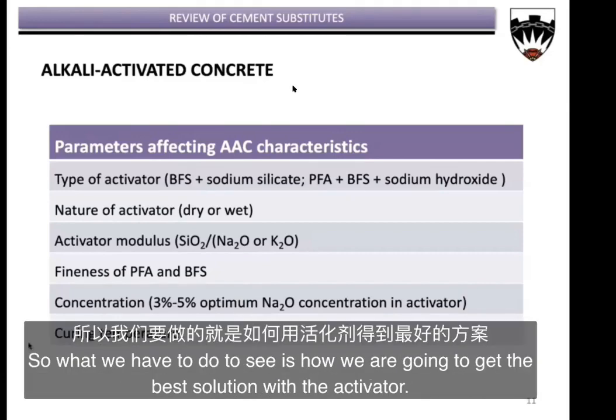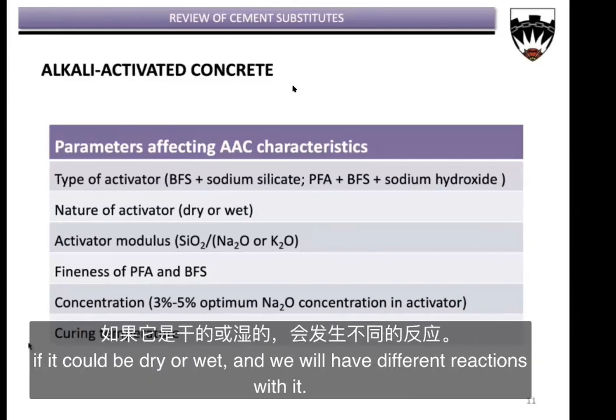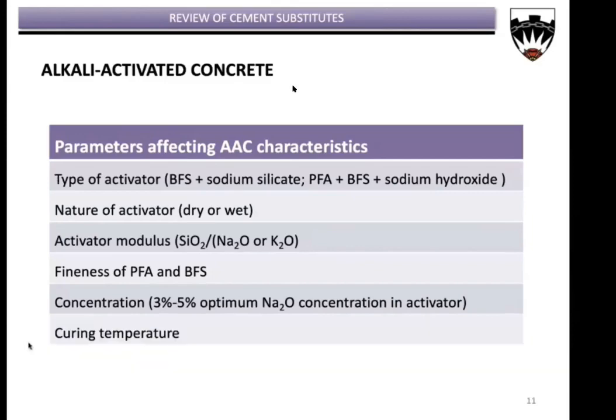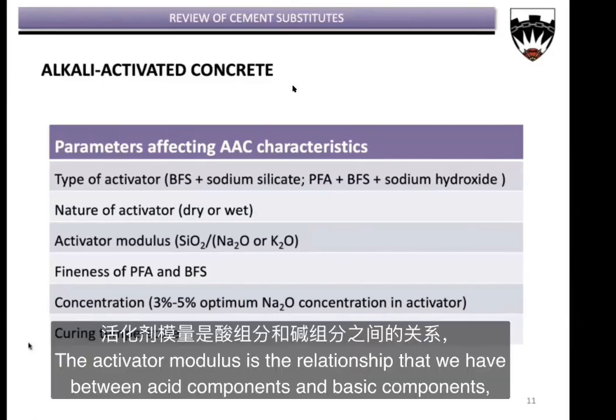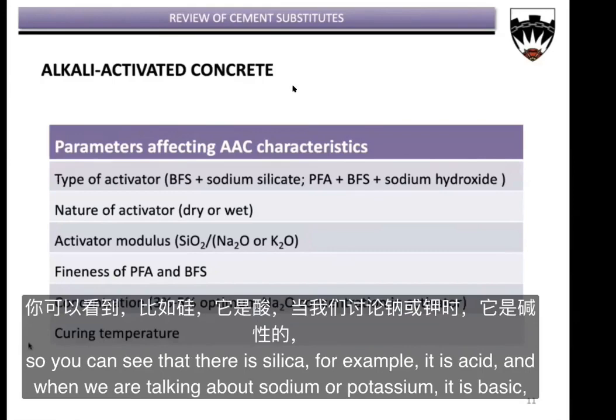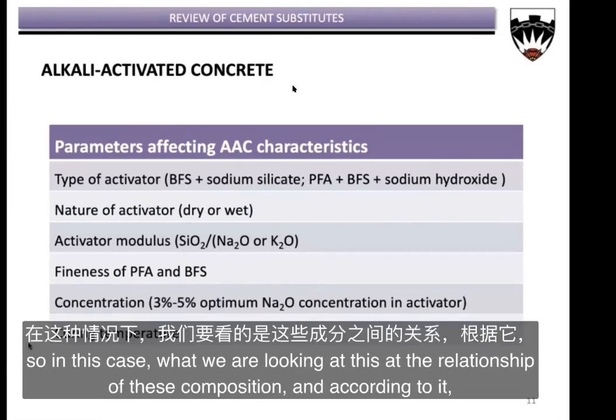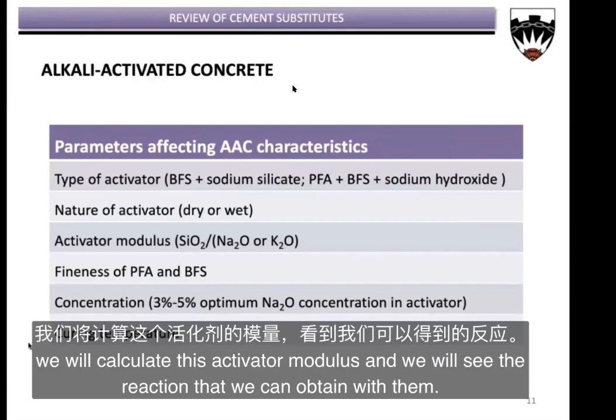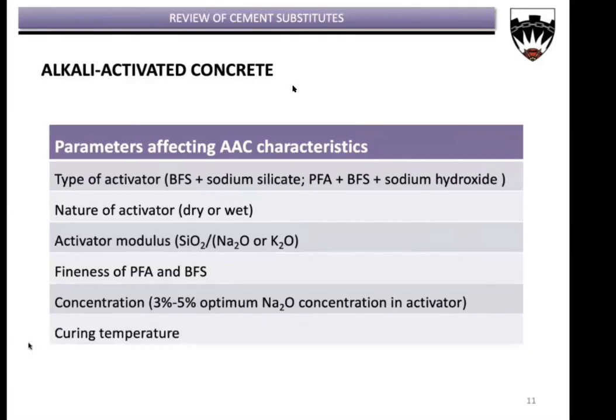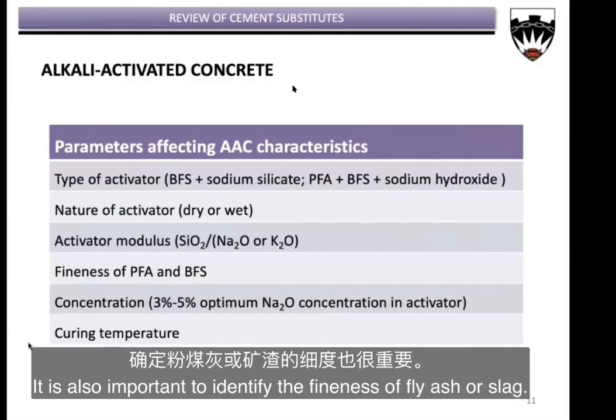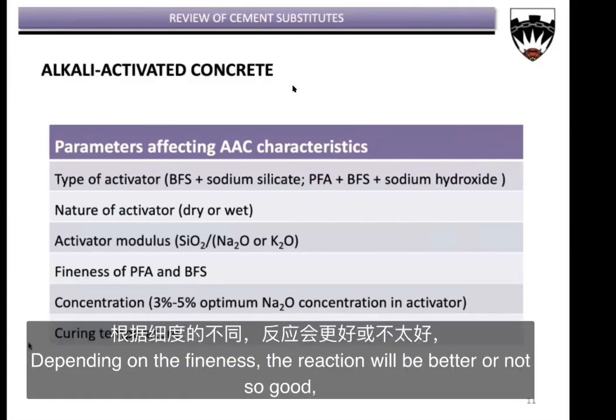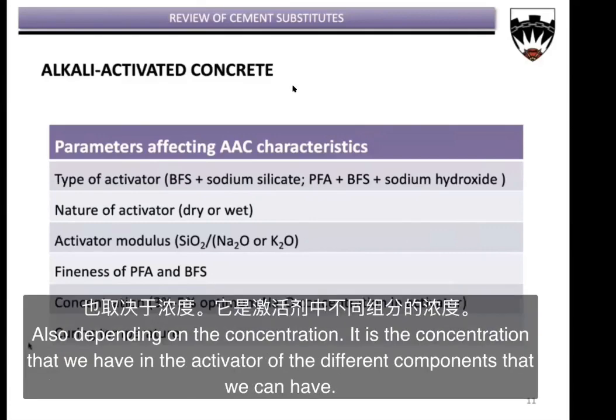So what we have to see is how we are going to get the best solution with the activator, if it could be dry or wet, and we will have different reactions with it. The activator modulus is the relationship that we have between acid components and basic components. So you can see that there is silica, for example, this is acid, and when we are talking about sodium or potassium, it is basic, or alkaline. So in this case, what we are looking at is the relationship of this composition. And according to it, we will calculate this activator modulus, and we will see the reaction that we can obtain with them. It is also important to identify the fineness of fly ash or slag. Depending on this fineness, the reaction will be better or not so good. Also, depending on the concentration that we have in the activator of the different components that we can have.